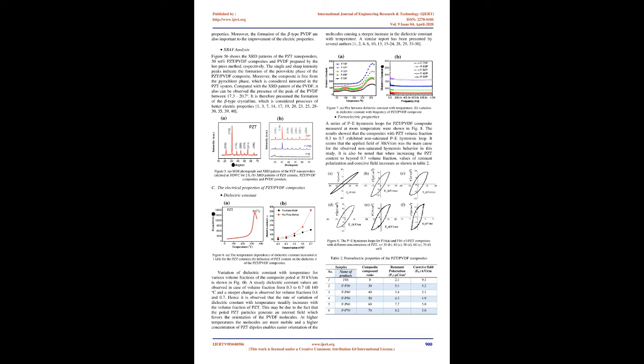Furthermore, the experimental density is smaller than the calculated one at fixed volume fraction of the PZT, which may result from the presence of pores in composites.